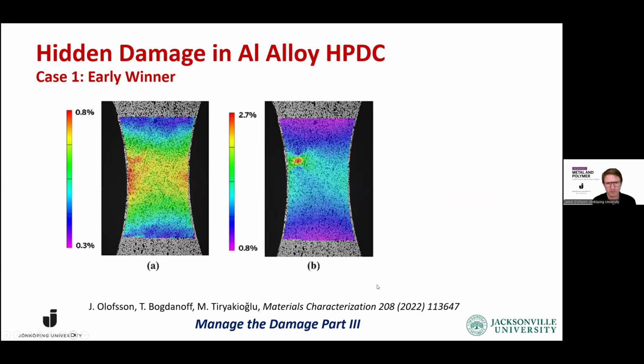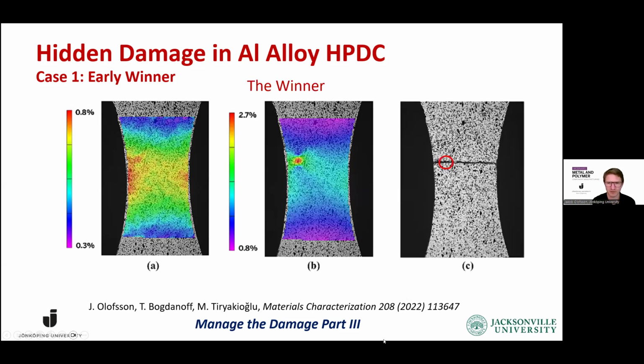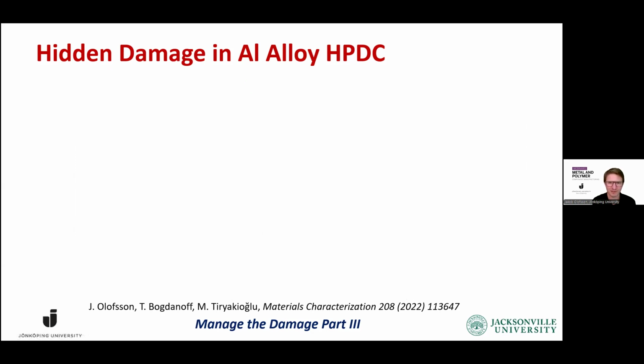So increasing the load, we can see that this spot actually clearly becomes the winner. The strain really increases much faster here than in the rest of the samples. And if we proceed to pulling it all the way to fracture, we can see that this is the point where the fracture is taking place. So we had a winner here in the race between the defects that was clearly rushing away from the start. It was a clear early winner here.